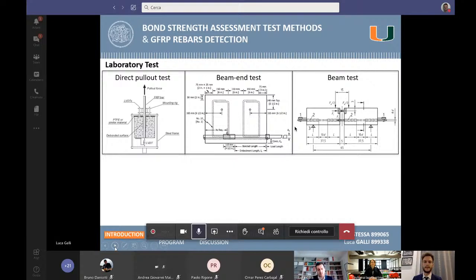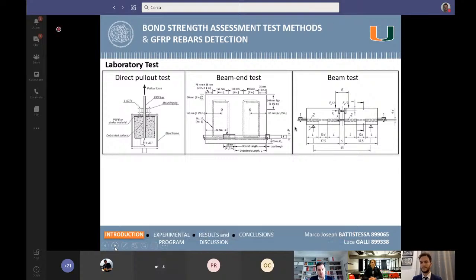Nowadays, different laboratory tests are used to assess the bond strength between the GFRPs and the concrete. Usually, specimens under accelerated exposure conditions are tested to evaluate and simulate the bond and the loss of performance over the long term. Among these test methods, the direct pull-out test is widely used because it is simple and requires only small specimens. Other tests, like the beam test, better simulate the real stress state condition of a reinforced concrete structure.